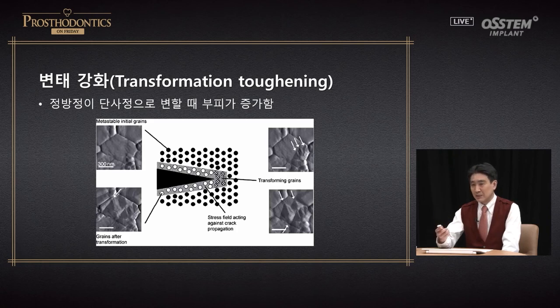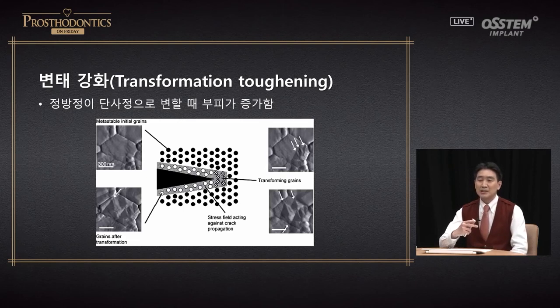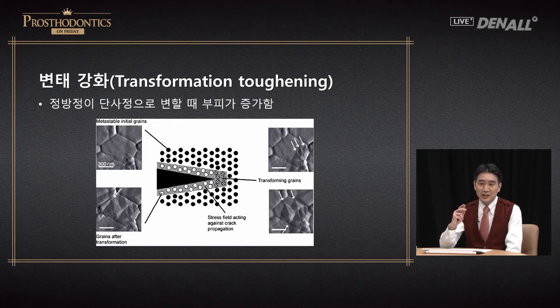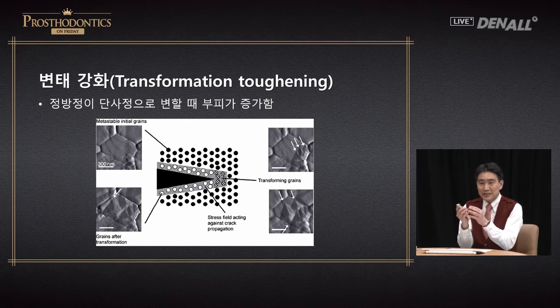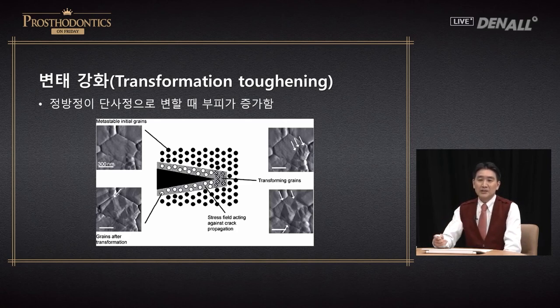Why does ceramic crack easily? You see that there's a crack. Once there's a crack, it progresses rapidly. That is the characteristic of ceramic, and that is why ceramic can break easily. As the crack progresses, because of this crack, tetragonal phase changes into monoclinic phase. Because the volume increases, the crack cannot progress. As it expands, the crack is stopped.